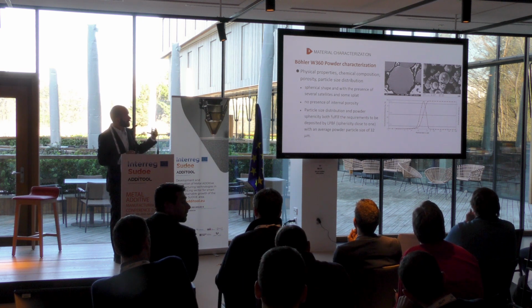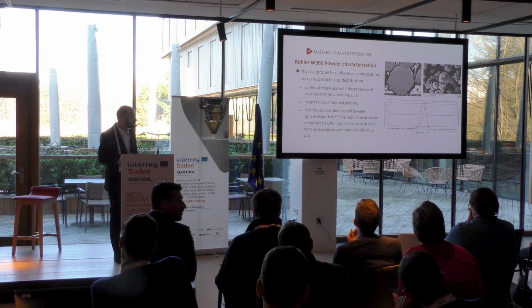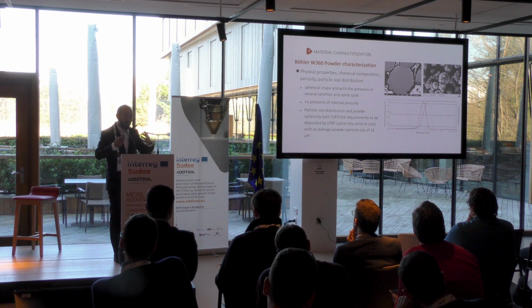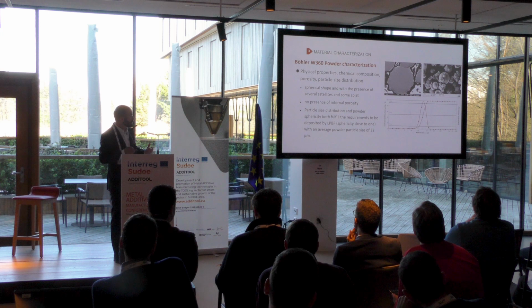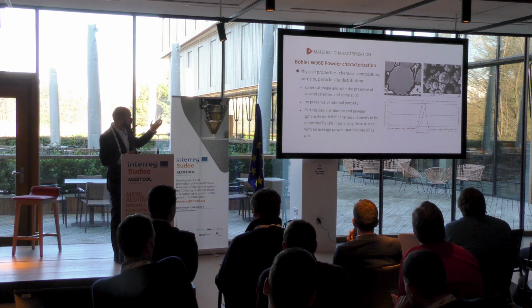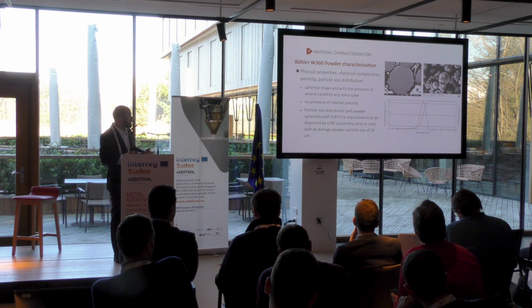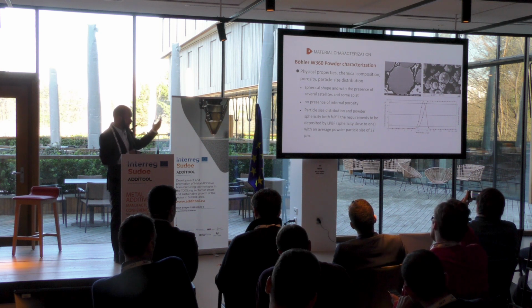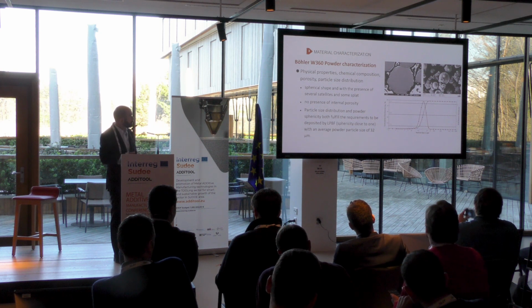Our partners at SEED, especially at ENIT, had some trouble testing the material due to its very high resistance, mechanical strength and hardness. The powder itself is more or less okay in terms of sphericity, and for laser powder bed fusion there's no problem.